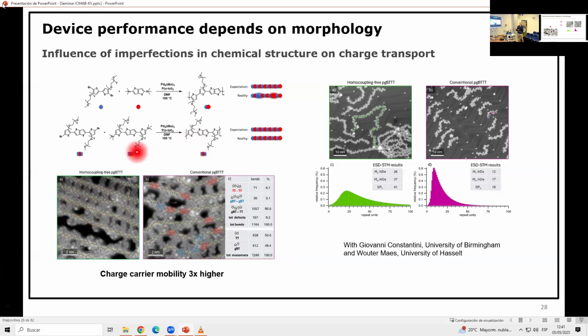This chemistry route also gives slightly higher molecular weight. And the mobility is 2 to 3 times higher. Actually, in this case, with this particular polymer, we try it now with all the polymers where this is possible. It's not always possible. And in some cases, we actually see worse performance for the perfect alternating one. So in some cases, you actually need those miscouplings. We do think it has something to do with the solubility.